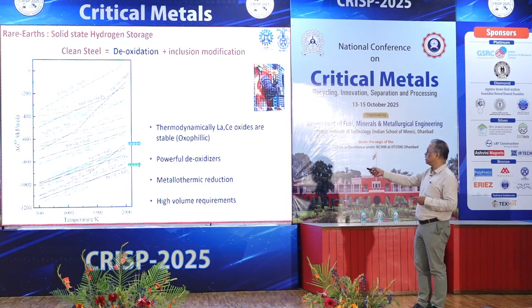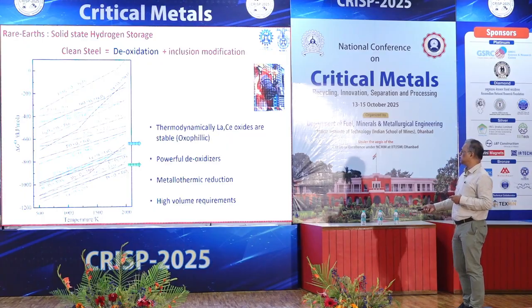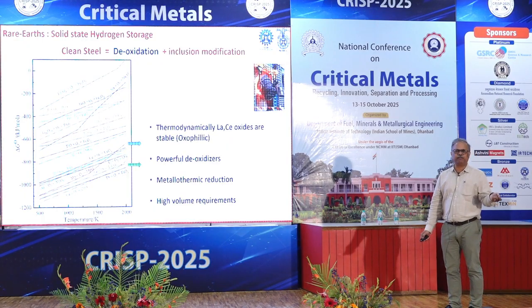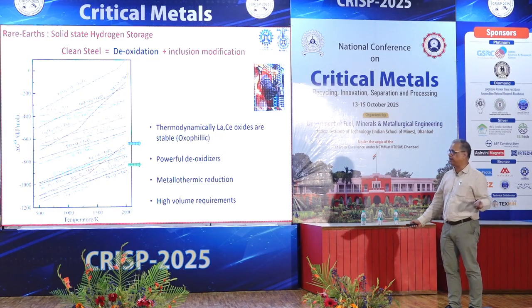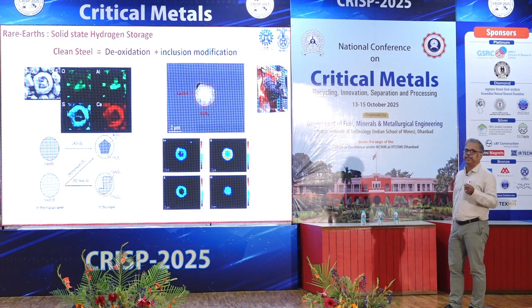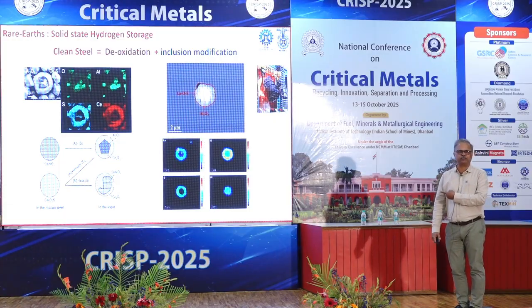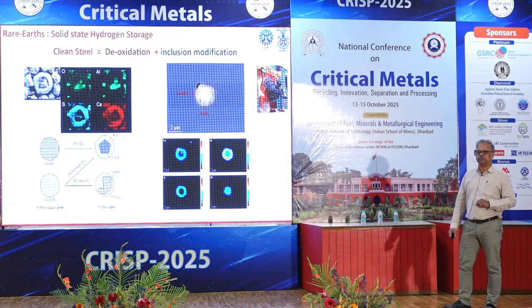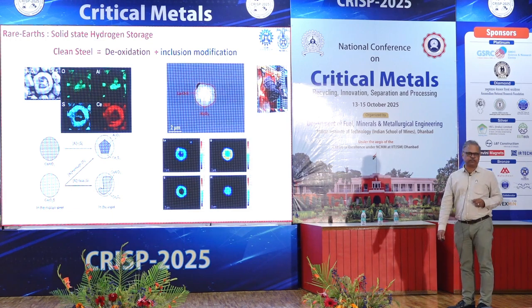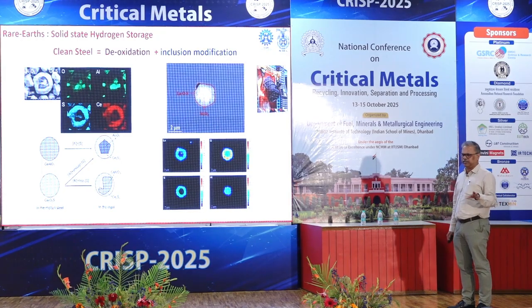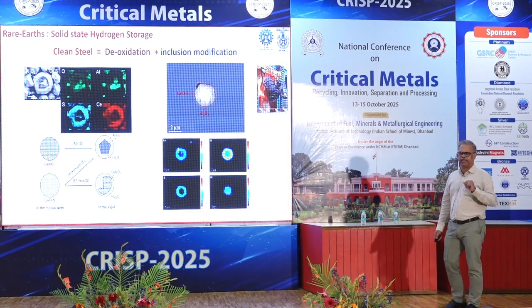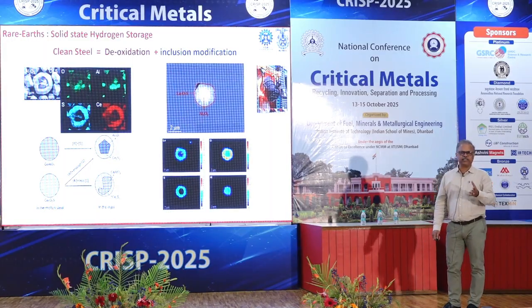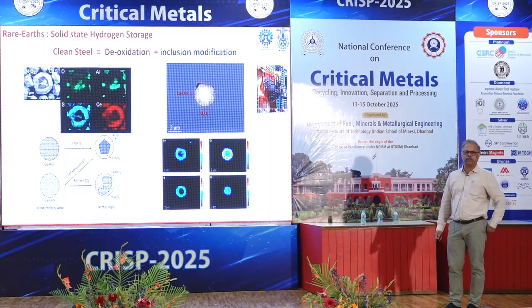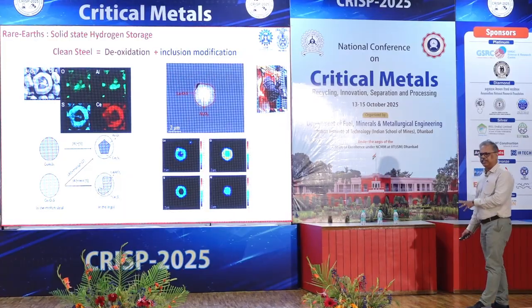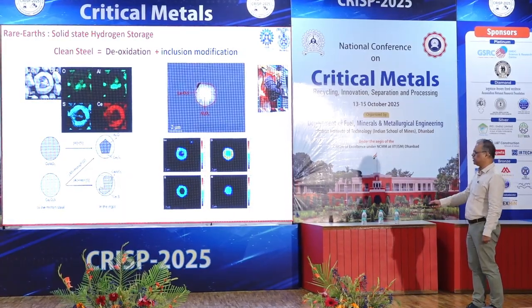Now for that, we have these Ellingham diagrams. Another thing is that when you have hydrogen in these materials, hydrogen embrittlement is a known phenomenon, and so is the toughness issue. For that, you should have no inclusions. Only if you use these rare earth materials can the morphology of the inclusions be controlled, and that can lead to good toughness of the material, not deterioration of the toughness. Today we have a project from IREL, thanks to them, to control these particular morphologies in the steel, so that the toughness is not impaired by hydrogen and others.